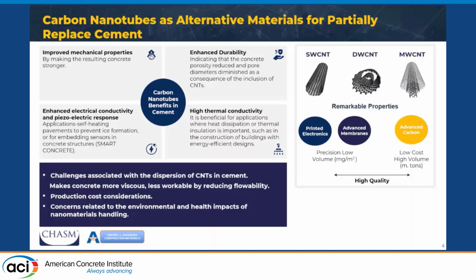However, there are some issues associated with the use of carbon nanotube in this application. One of the challenges is how to disperse these materials in an efficient manner, because nanotubes tend to form bundles and ropes that, when you try to disperse the material in the cement, agglomerate, making it less workable and reducing the flowability properties. And there are some other issues concerning the cost of this material and the production at large scale. And there are some concerns related to the environmental and health impact of this material during its handling. And these are precisely the three main areas that we at Chasm are trying to address and to solve.